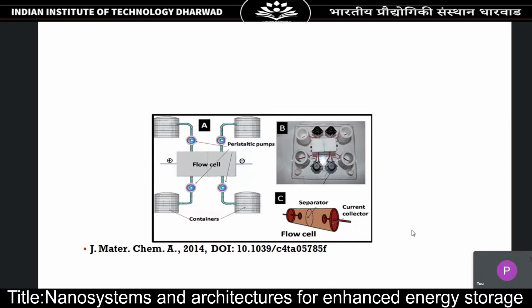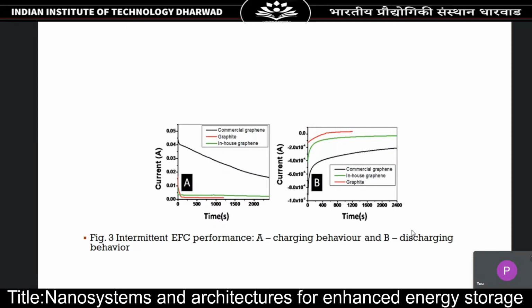So this is the structure which was made to construct the electrochemical flow device. You can see that the flow cell is very simple. It has got the current collector and the electrode, and there is a separator in between. And then it is housed in the center of the device, and it is connected to 4 peristaltic pumps, which drive the slurry from the container. For example, the flow of electrolyte into the cell and out of the cell is determined by the peristaltic pump. This device was made in the laboratory, and it was also published in Journal of Materials Chemistry. So, this is the chronoamperometry